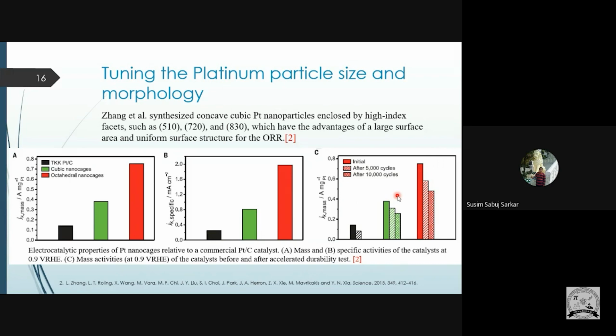So we are trying in this way, but after lots of cycles, using this platinum more and more, as time goes on, this nano cage structure ultimately transforms into a spherical structure. So after a certain point of time, the activity decreased a lot. That means it's not very effective.